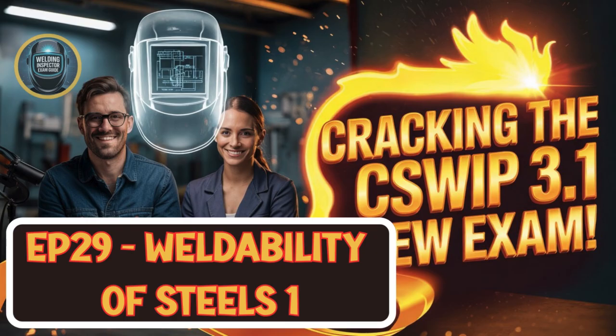Yes. Alternatively, you can use stabilized grades, like grade 321, which contains titanium, or grade 347, which contains niobium. Stabilized. How do they work? These added elements, titanium or niobium, have a stronger affinity for carbon than chromium does. So they preferentially combine with the carbon to form titanium or niobium carbides instead of chromium carbides. They effectively act like bodyguards for the chromium, preventing its depletion at the grain boundaries.